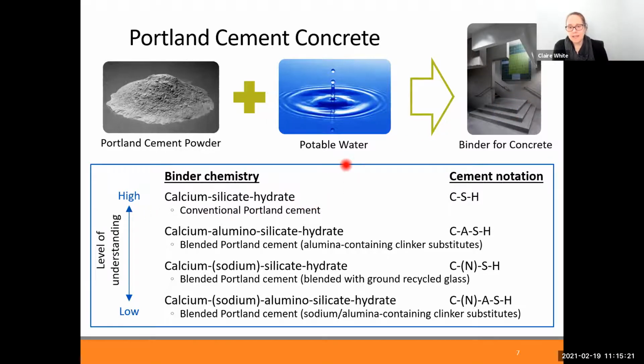So what's happened is that originally calcium silicate hydrate gel was the main binder phase that holds concrete together. And up until about, I would say, 100 years ago, most concrete was mainly based on this gel in terms of the strength-giving phase. But in recent decades, people have started substituting what's called supplementary cementitious materials into concrete, which changes this fundamental gel. It changes the chemistry of the gel, and so then it's possible that it's also changing things like its thermodynamic properties.